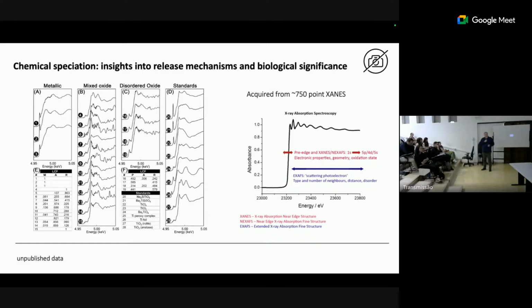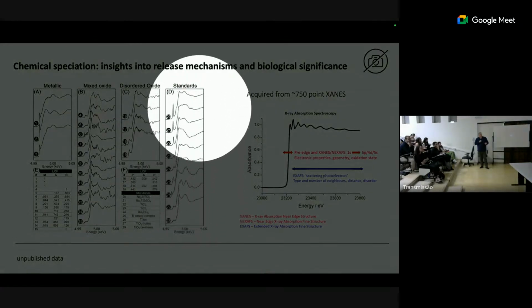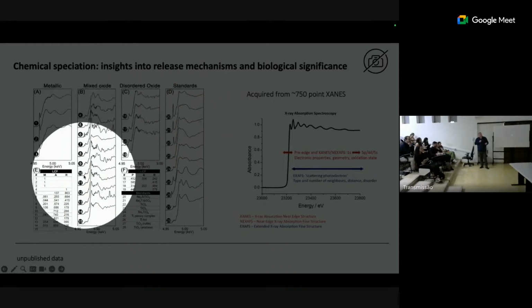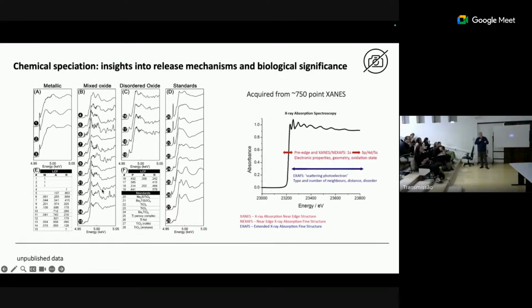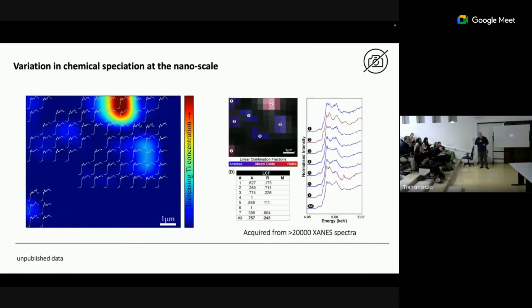We covered it a little bit with the tooth study, where we can start to get fingerprints for individual metallic elements. And what we tend to do is work against standards, which we know exactly what those materials are. We can compare what we find from the tissues, and then we start to develop an understanding. And what we find is that you have highly mixed species, with high chemical variability at submicron levels, but they principally form into two types. They're either crystalline oxides or they're amorphous mixed species. But that doesn't necessarily help us that far in this story, so we have to go even further.